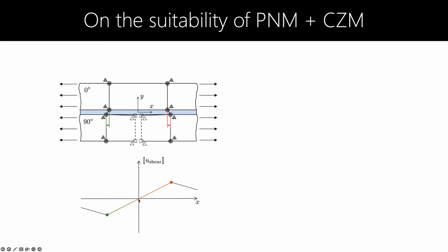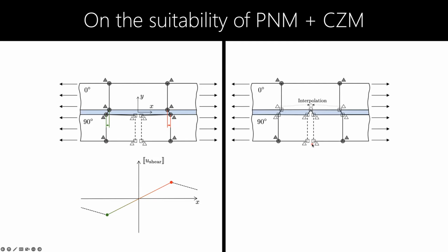If you have more than one integration point, it will fail at some point, but clearly at a much delayed moment. So ideally, what you would like to have is that when this element fails, the cohesive element itself splits in two so that you actually don't lose that concentration. So in that case, you'd have still the same displacement jump at one end and at the other, but now you'll have a bigger jump at the end, which allows you to simulate this transition to delamination, which is key to capture if the delamination is itself then important for the final failure of the laminate.